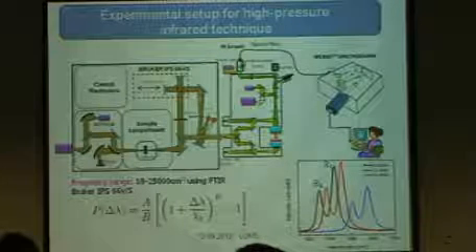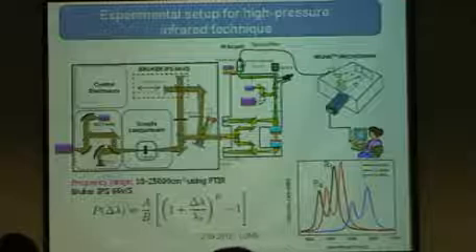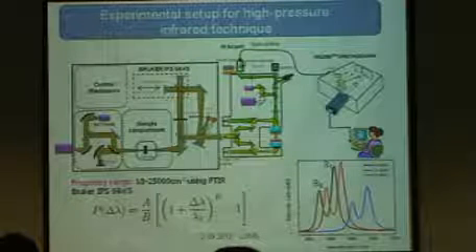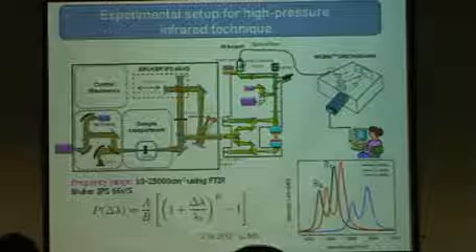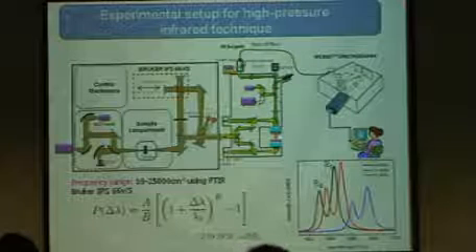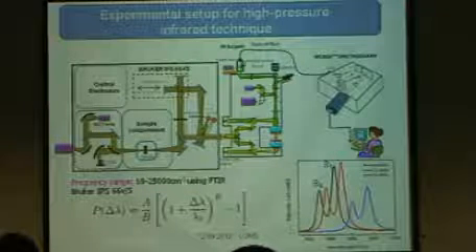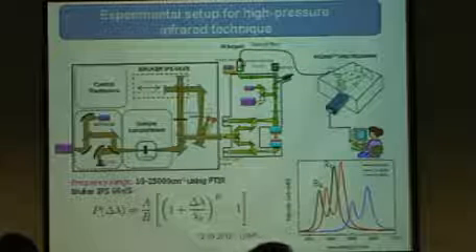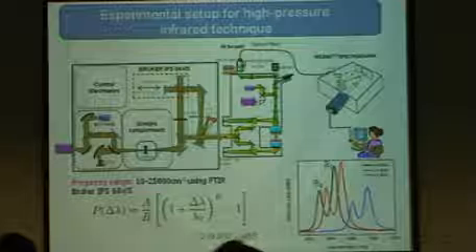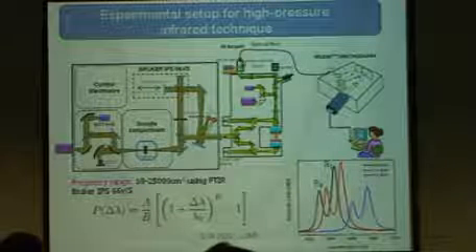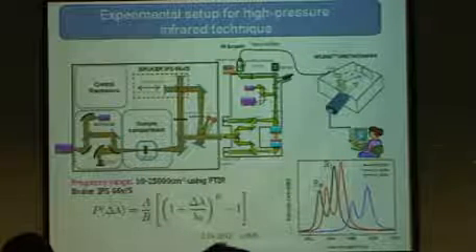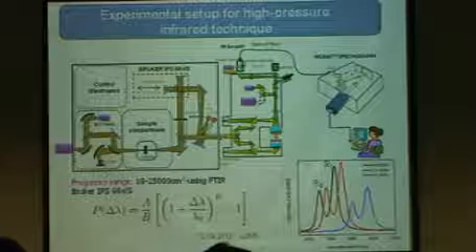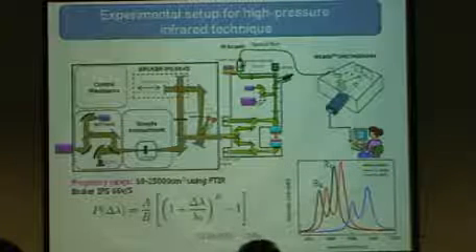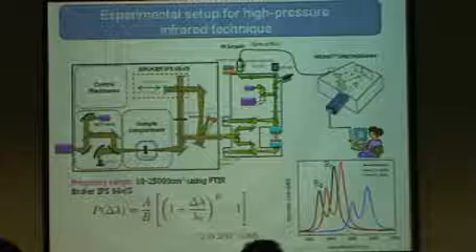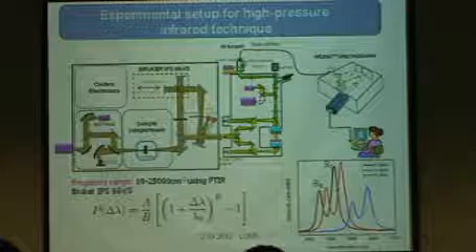For pressure measurement, you shine a green laser and excite a ruby crystal within the chamber of the pressure cell. Then you get a fluorescence signal, which you collect and send to the spectrograph through an optical fiber, where you measure the pressure. The pressure is measured using the characteristic ruby lines, called the R1 and R2 lines. These are very sensitive to temperature and pressure, so when you change the temperature or pressure, you see a shift in the frequency position of these two lines.